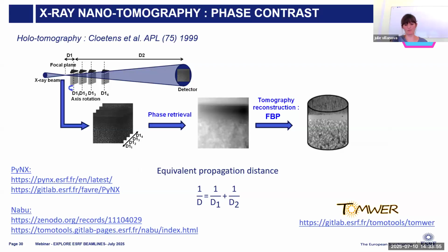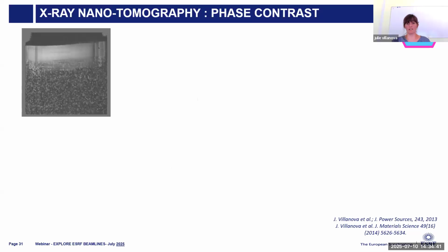The main acquisition mode we use to perform the phase contrast imaging is the holotomography technique, which consists of acquiring 4 times the same tomography, changing slightly the propagation distance. According to this equation, it means for us just moving a little bit the sample along the X-rays. Then what we do is that we align the 4 images for each angle of the rotation. And then thanks to phase retrieval calculation, we create those so-called phase images. And then from those phase images, we use most of the time a filtered back projection algorithm to reconstruct the 3D volume.